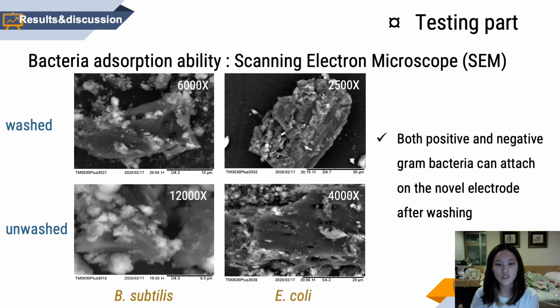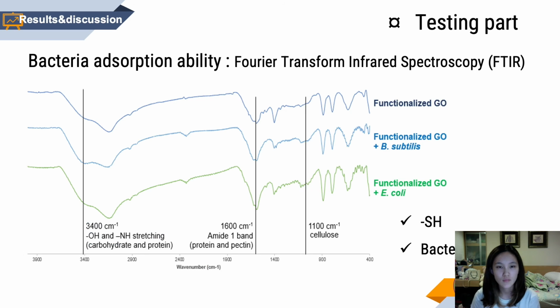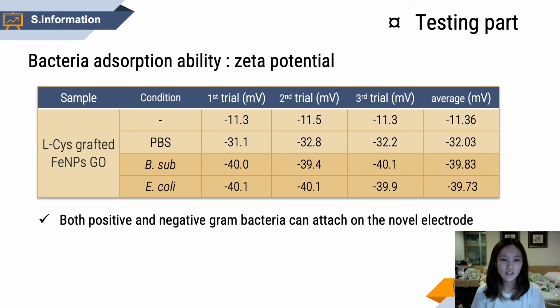SEM results also suggest that after washing, there are still some bacteria on the graphene oxide sheet for both gram-positive and gram-negative bacteria. FTIR can confirm the presence of the sulfide group and bacterial cellulose. And the zeta potential of the L-cysteine graphene iron nanoparticles in bacterial solution decreased significantly from the control one for both B. subtilis and E. coli. These results can be concluded that our novel electrode can actually trap the bacteria.